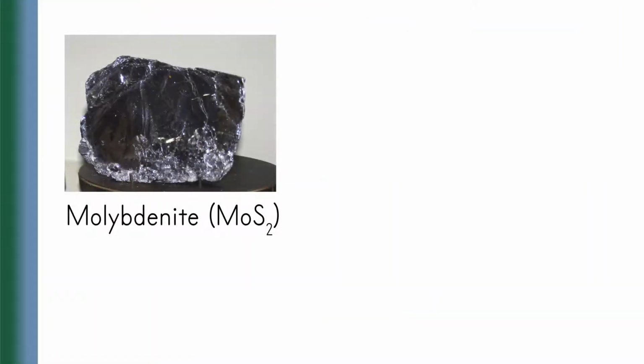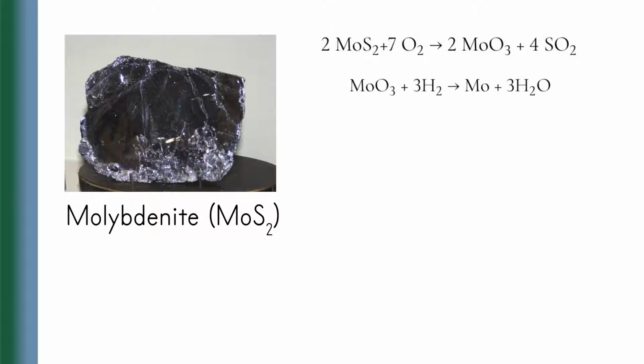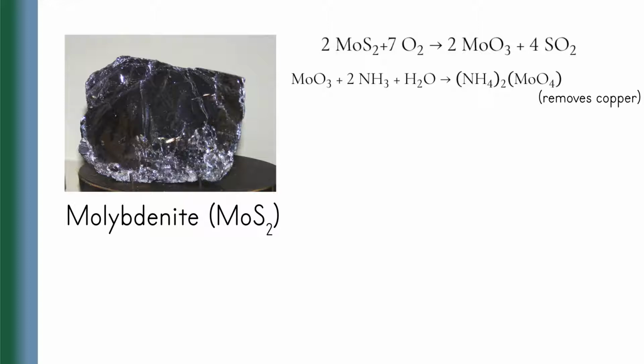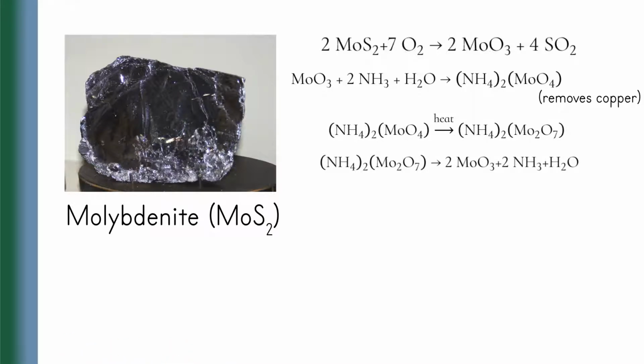For molybdenite, the sulfide is roasted so it becomes oxide. This oxide can be reduced with hydrogen gas at around 600 degrees Celsius. But there is actually a step to remove contaminants, usually copper. The molybdenum(VI) oxide is dissolved in ammonia, where copper is less soluble. And to completely remove it, the copper is precipitated with hydrogen sulfide. This ammonium molybdate, after several steps and heating at the end of it, is turned back into Mo(VI) oxide again. Again, MoO3 and H2, but now the molybdenum(VI) oxide is purer.